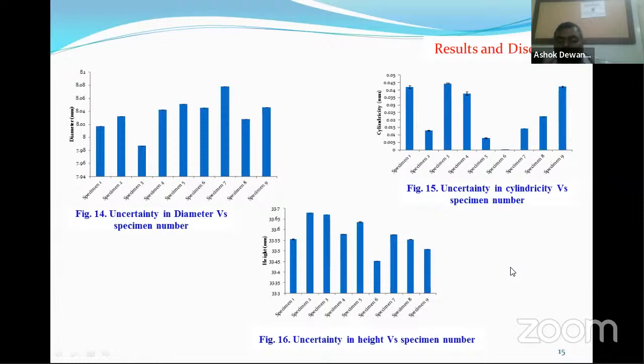Your height should have been 34 mm, but in none of the cases did you get 34 mm. Your diameter was supposed to be 8 mm, but your diameter is varying from 7.98 mm to 8.08 mm.